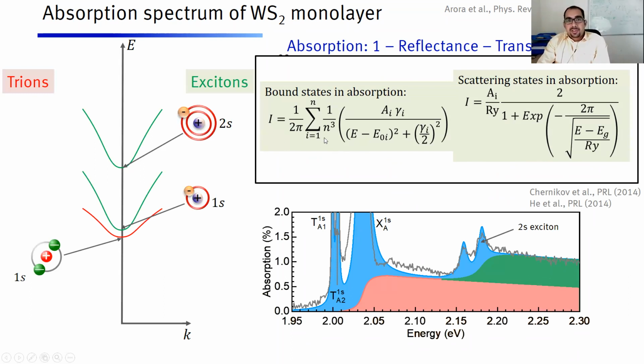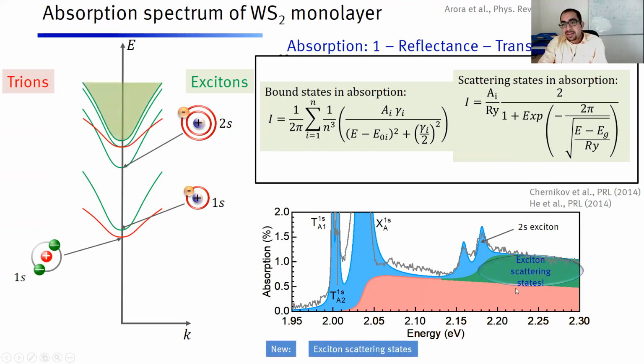So we use just Lorentzians to simulate the bound states and then these step-like functions with Sommerfeld enhancement to simulate the excited states. So these are the trions. We know that already. So these are these 1s trions. This is the 1s exciton. Now there is a 2s exciton, which is visible here, the excited state of exciton, which was not visible earlier in a quantum well, the excited state. And this 2s exciton is this one, right? And after that, there are these scattering states of excitons, which are these shaded regions.